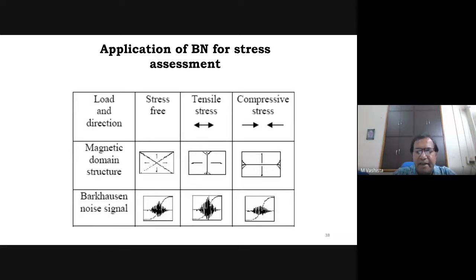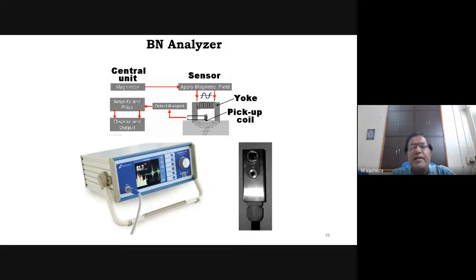Schematic diagram indicates that tensile residual stress will increase the Barkhausen noise signal level. This is the Barkhausen noise signal level from a stress-relieved material or stress-free component. If it has compressive residual stress, then definitely the level of Barkhausen noise signal will significantly reduce. So by using this technique, we can also assess the residual stress.